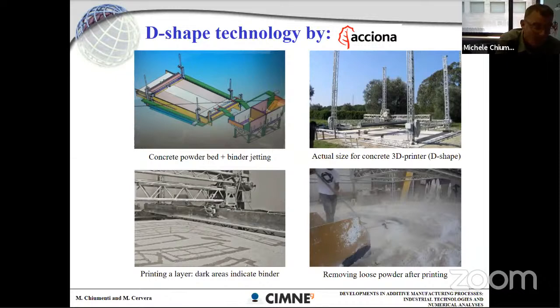As you can see, it is a powder bed technology, so once again, similar to the one for metal or for plastic. In this case, you are selectively wetting the powder, the concrete, and they are using one kind of binder. And once the material solidifies in a layer by layer manner, at the end of the process, they remove the loose powder, and you can obtain the final structure. So it is quite a different technology from the previous one, and the numerical tool should follow different criteria.